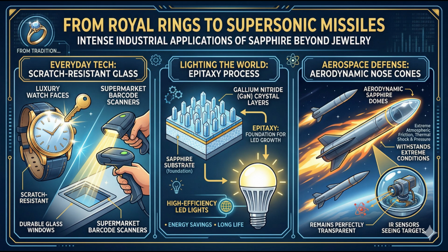It's like a microscopic architectural blueprint. Exactly. Gallium nitride has a hexagonal crystal lattice, and as we discussed, sapphire also has a hexagonal lattice. So they match up. While the alignment isn't mathematically perfect, it is close enough to facilitate the growth. But more importantly, the process of depositing gallium nitride involves extreme heat and highly corrosive precursor gases. Oh, and because sapphire doesn't melt until past 2,000 degrees and doesn't react with the corrosive gases, it survives the manufacturing oven perfectly intact. It does.